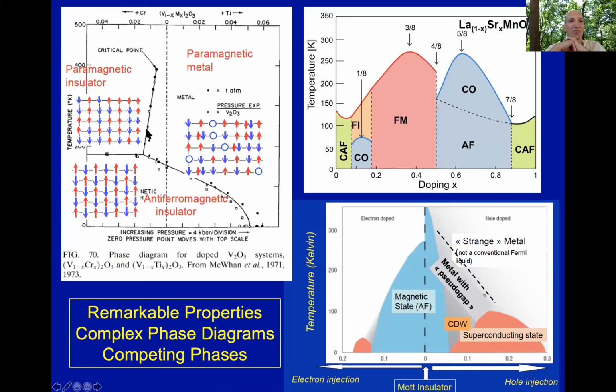You have a phase here, which is that of a paramagnetic insulator. I called it paramagnetic because it has fluctuating local moments. So you can think of the cartoon of the wave function of electrons in this material as just localized electrons on their crystal lattice sites with random spin orientations. If you look closely, the blue and red arrows are more or less randomly distributed. And as you increase pressure, if you are below 400 or so Kelvin, this material would undergo an insulator to metal transition through a sharp first order line where the resistivity actually drops by several orders of magnitude. And so what you reach here is a metallic phase, which is conducting. This is depicted in a cartoonish way by having also places where there are holes and double occupancies so that electrons can more easily move around. So this is a non-magnetic metal.